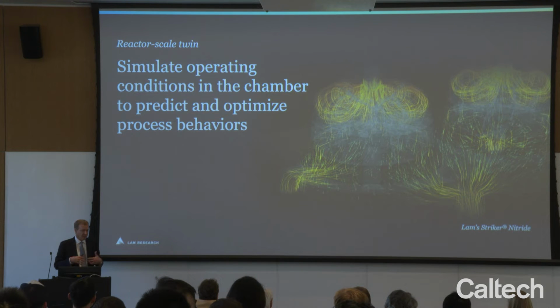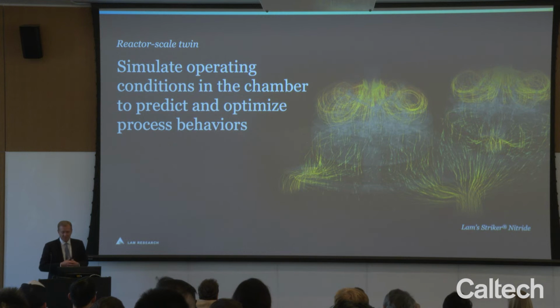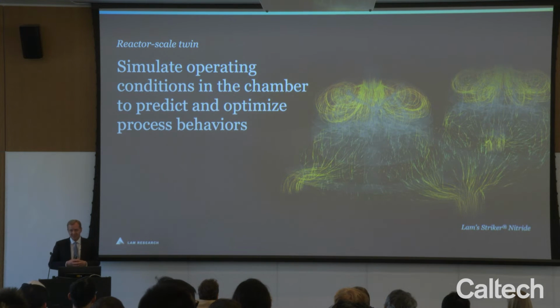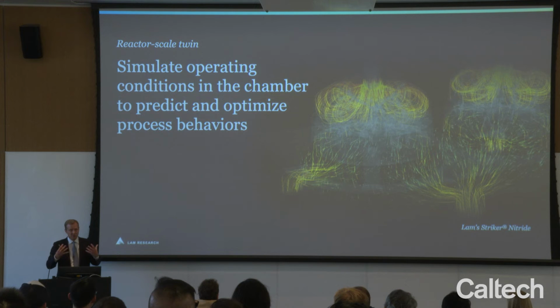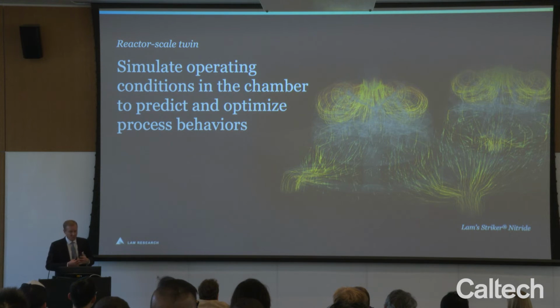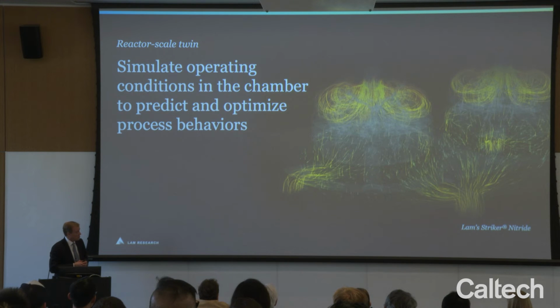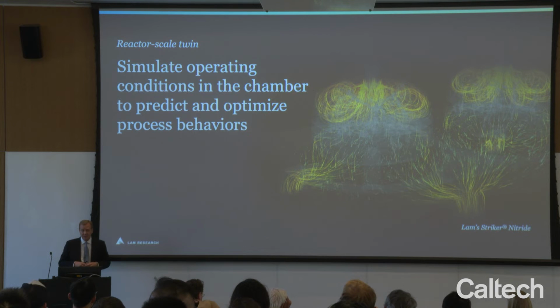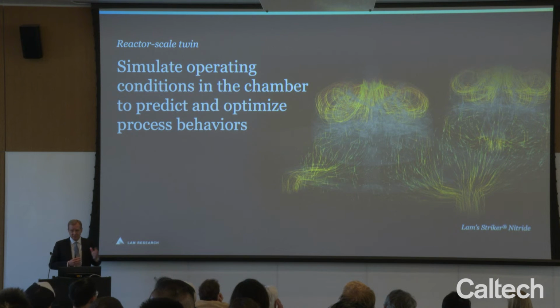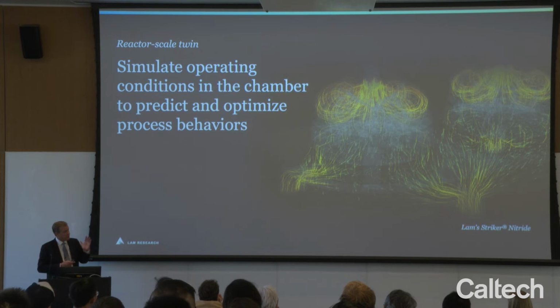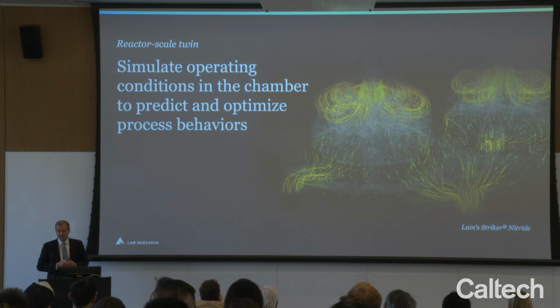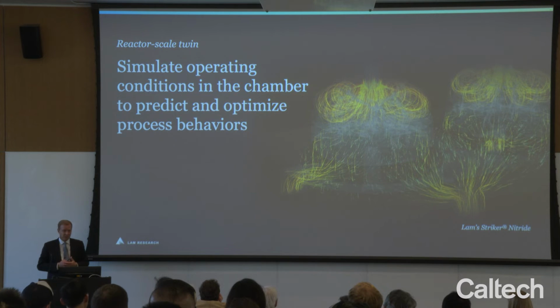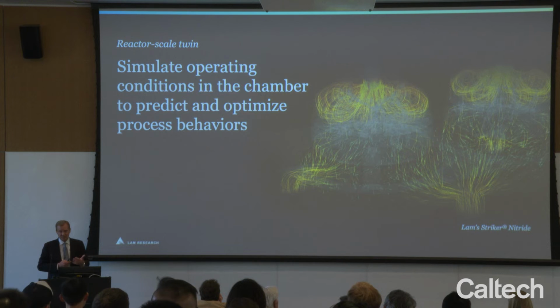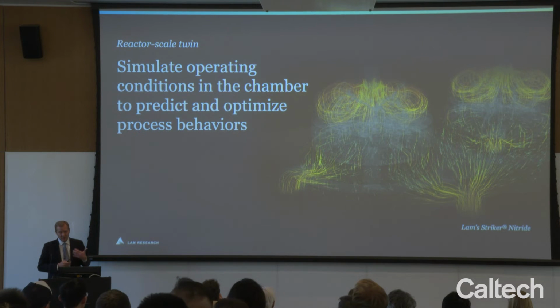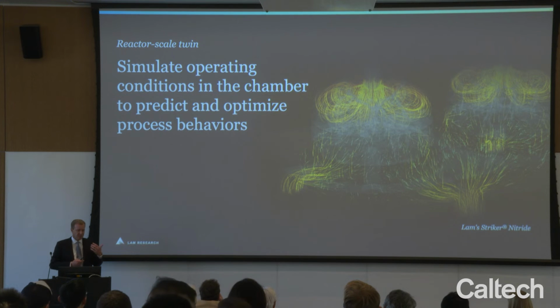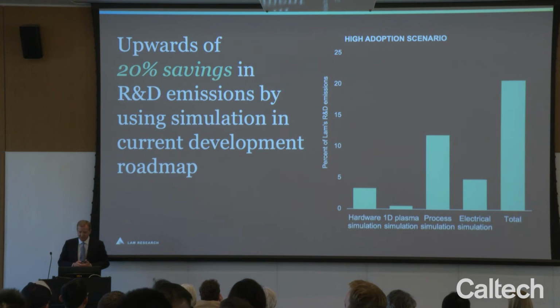We're creating virtual twins that allow us to visualize the plasma behavior and reactor design dependencies. Again, the same idea. Engineers are able to virtually test different hardware configurations. What you're seeing here is a simulation of what's happening inside a Lam Striker nitride tool. This is a tool that does atomic layer deposition of nitride films in advanced devices. By using this new hardware simulation, we've been able to shorten the time for hardware design iterations by 8 times and reduce the design cost by 5x. So again, very powerful means of helping address the speed and the cost of innovation for semiconductors.